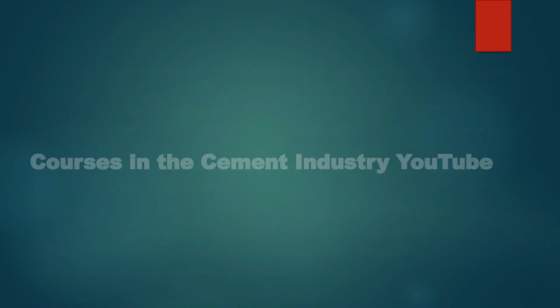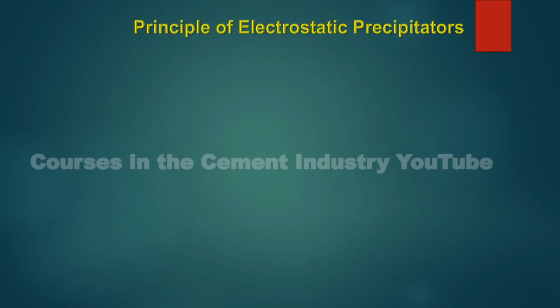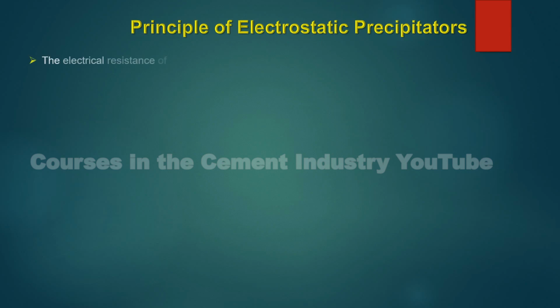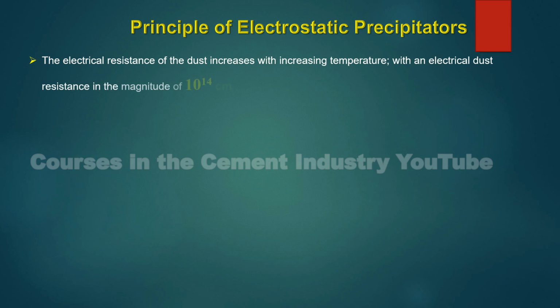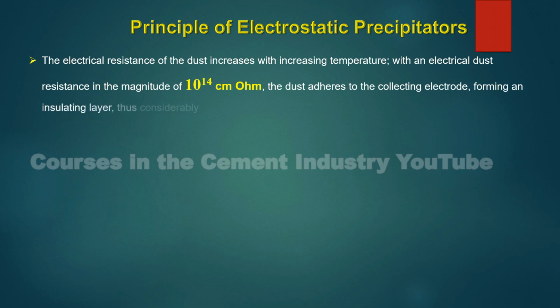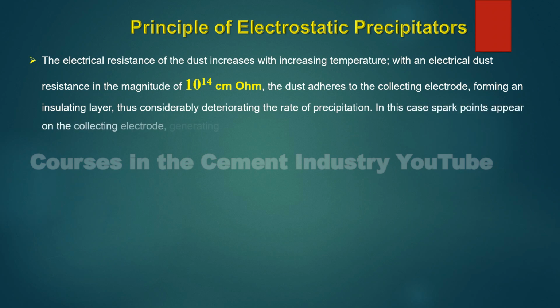Principle of electrostatic precipitators. The electrical resistance of the dust increases with increasing temperature, with an electrical dust resistance in the magnitude of 10^14 ohm-centimeters. The dust adheres to the collecting electrode, forming an insulating layer, thus considerably deteriorating the rate of precipitation. In this case, spark points appear on the collecting electrode, generating reversed ionization.